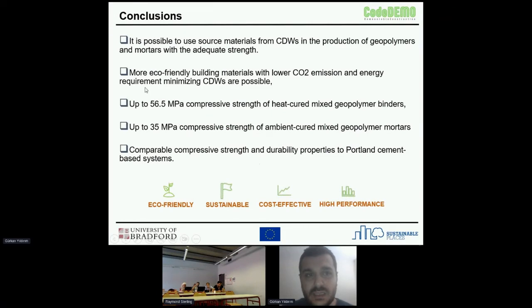So as a conclusion, we managed to show that it is possible to develop concrete mixtures and mortar mixtures with significantly lower CO2 emissions and energy requirement with complete construction and demolition waste. And we were able to reach compressive strength levels and suitable durability properties comparable to traditional Portland cement-based systems.